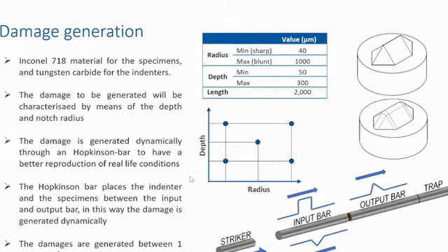So the first step of the project was to plan our damages and our indentation. We identified as key parameters for the damage the depth of the damage and the radius of the tip, and the ranges that were given by GKN, the topic manager of the project, were for the radius between 40 micron and 1000 micron, and for the depth between 50 micron and 300 micron.